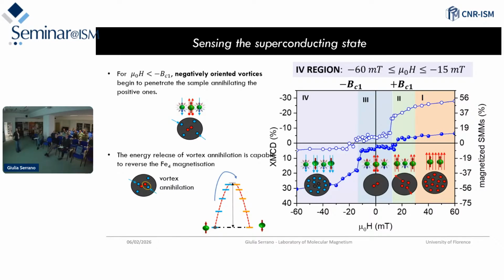Because what we observe here is that almost suddenly the magnetic signal from the molecule passes from roughly minus 5% to plus 5%. So we suppose that all the molecules with the up magnetization reverse their magnetization to the down magnetization. So this is quite nice because it confirms that molecules can also probe vortex dynamics, including trapping and pinning. And we could also think about playing with vortex annihilation to control the magnetization of the single molecule magnets.